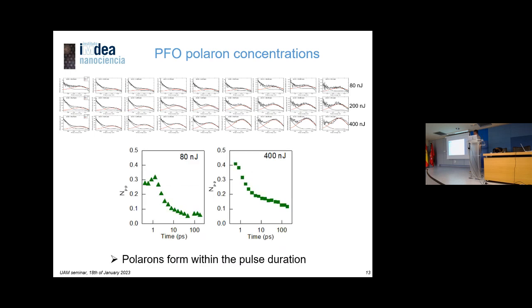Another way to see it, we can obtain the polaron pair per absorbed photon, for 2 different energies. As you can see, in this polymer we already form these polaron pair species on very fast timescales, within the pulse duration.